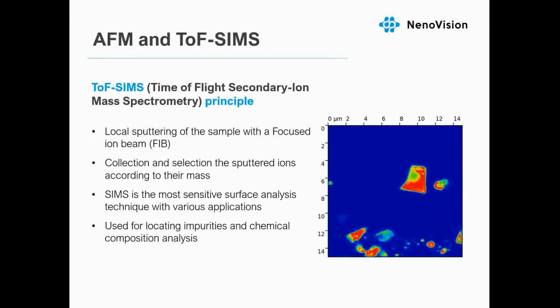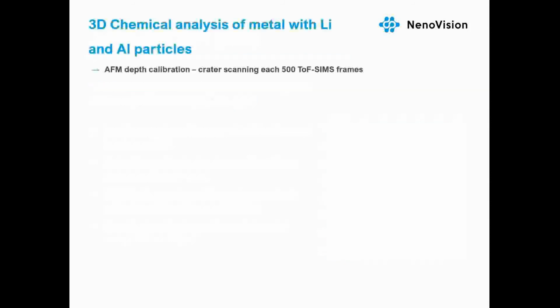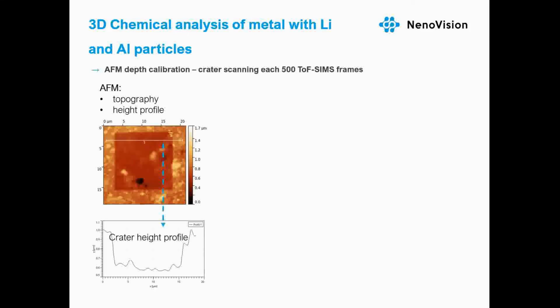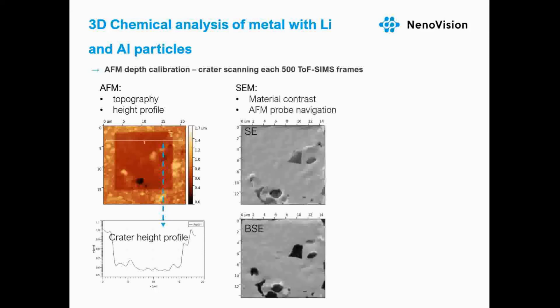LiteScope integrated into the FIB-SEM system was used to analyze the sputtered structure every 500 frames, and the resulting topography was subsequently correlated with the elemental map provided by TOF-SIMS and SEM material contrast. The result of the elemental analysis was three maps: AFM topography with height profile, material contrast provided by SEM. SEM was also used to precisely navigate the AFM probe. And lastly, the elemental distribution by SIMS.